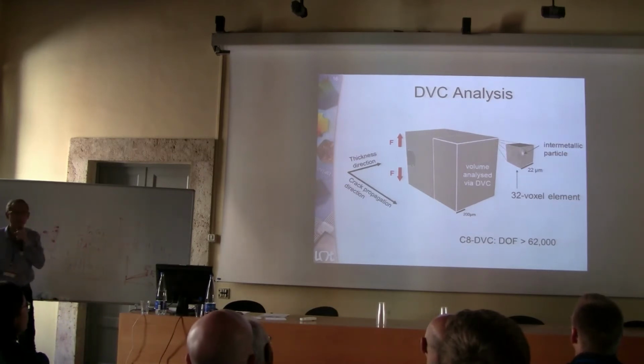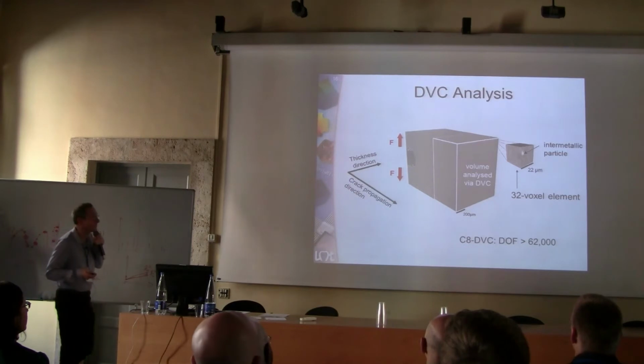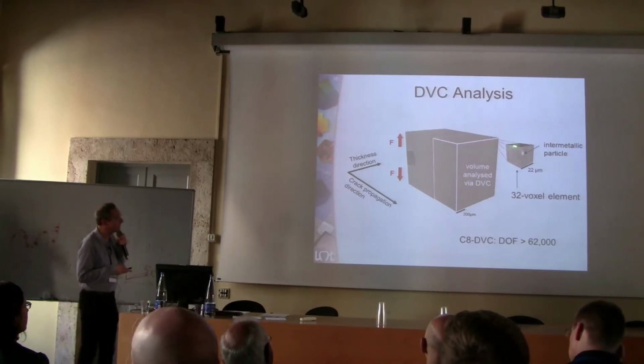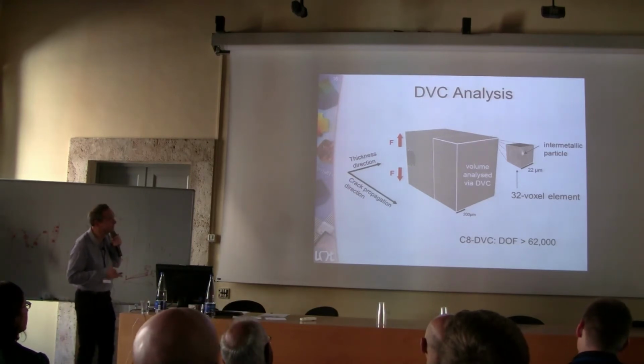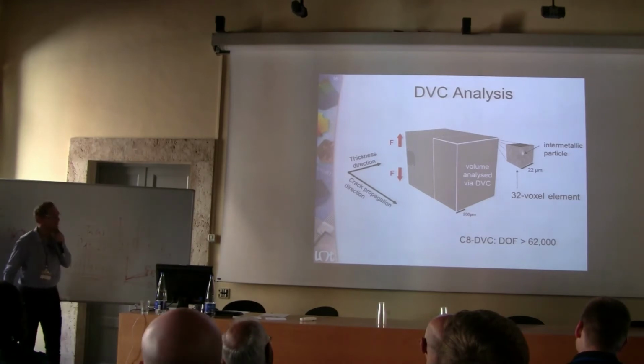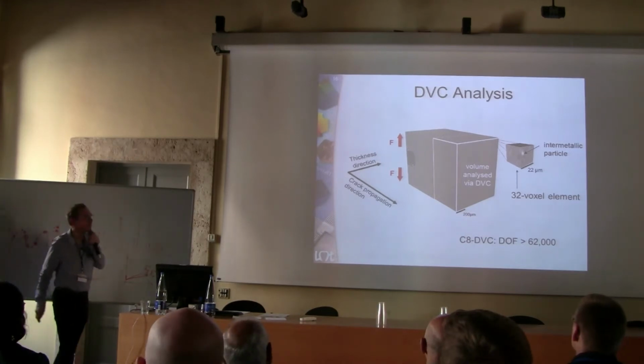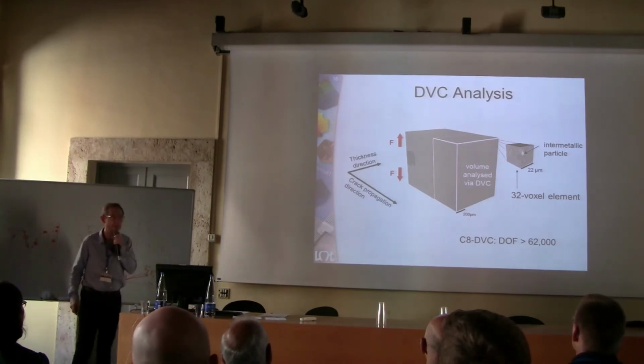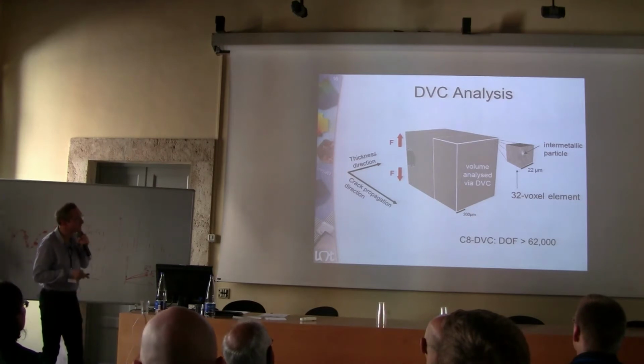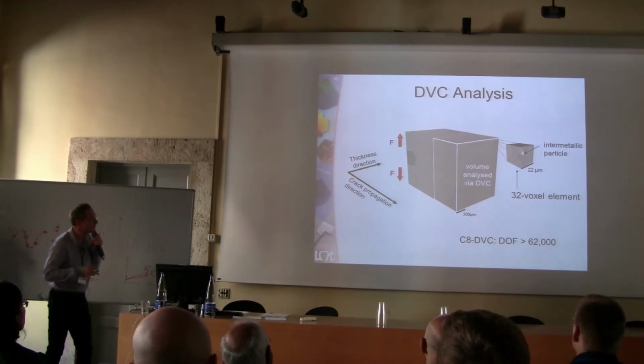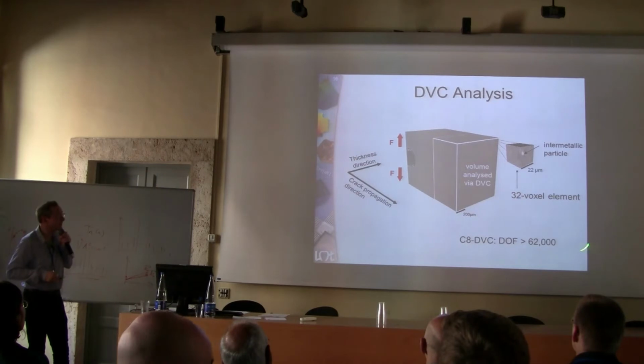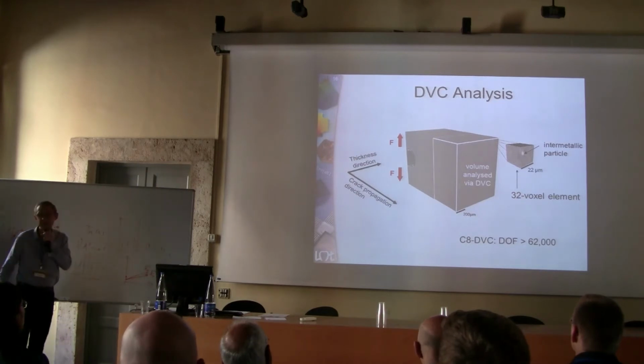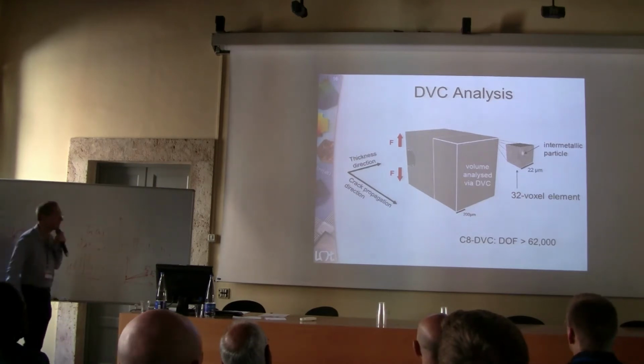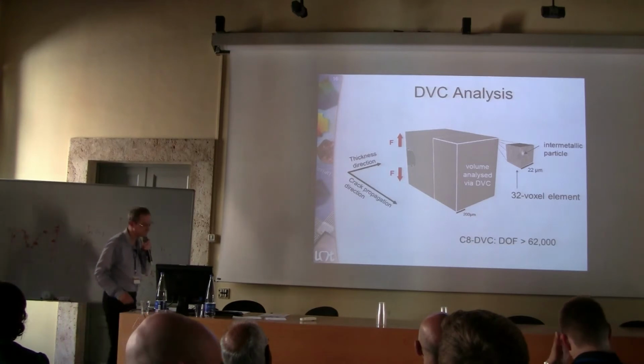Each voxel size was 0.7 micrometers. In this material, you see there are not so many markers - at least it's less than 0.4% volume fraction. But still, we tried to use DVC, and in this particular example you have access to something like about 60,000 degrees of freedom.